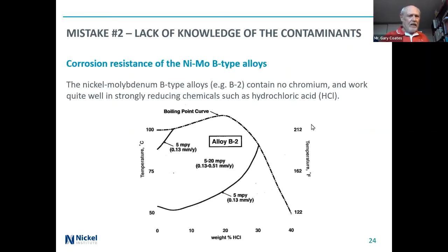So if you were listening to any of the earlier ones on the nickel alloys, the nickel molybdenum alloy contains no chromium, and works well in strongly reducing chemicals such as hydrochloric acid. Here's an isocorrosion curve, and even in boiling solutions of hydrochloric acid, the B alloy performs very well.